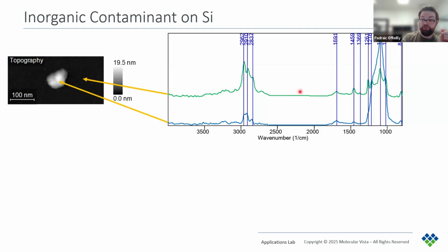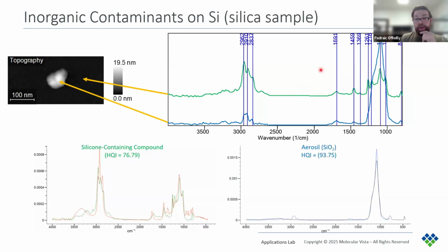There are many more peaks here than one would expect for a clean silicon wafer substrate. Now we can run these spectra again in IR databases. And we found that the thin contaminant on the wafer is a silicone, so a siloxane-based compound, which is actually something we find quite often on wafers. And the particle is identified as silica.